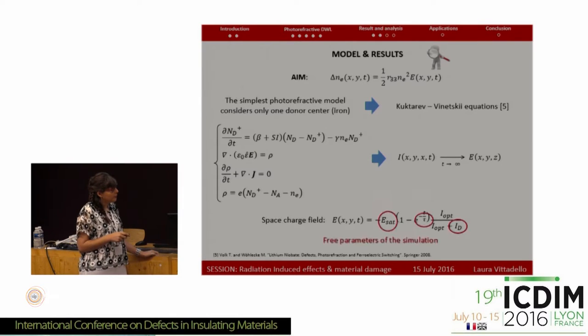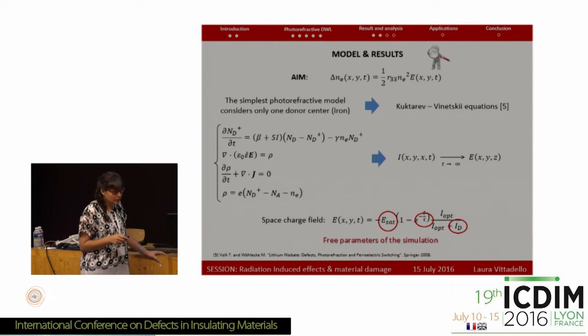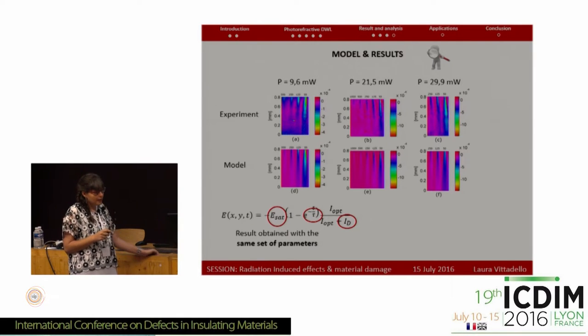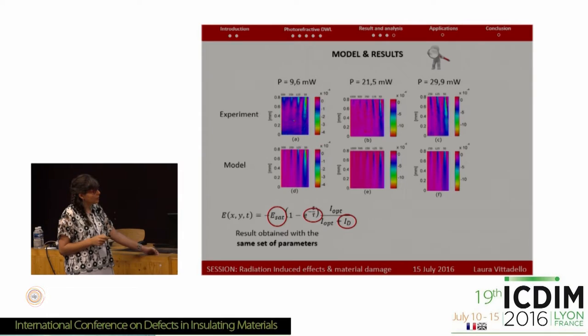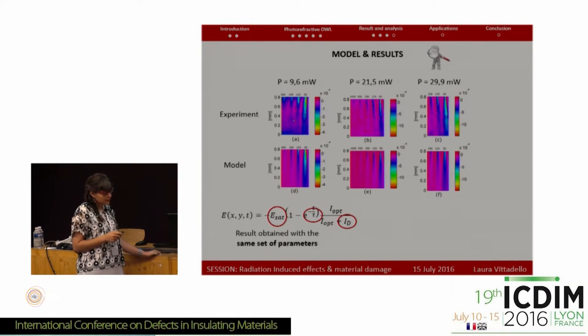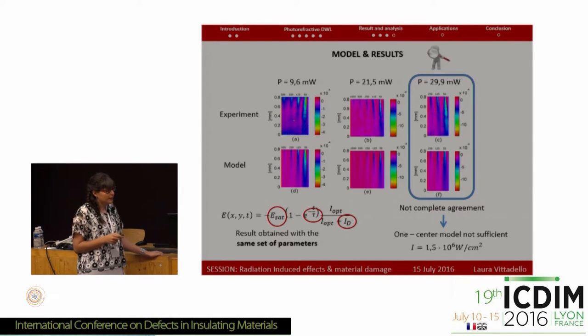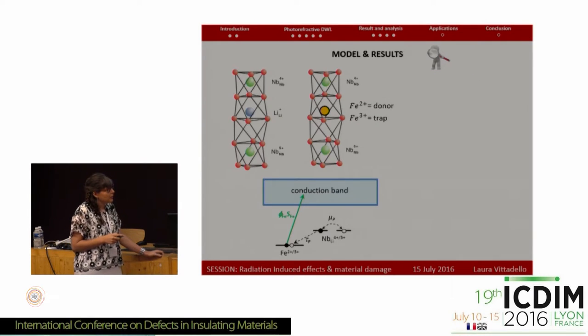In the formula there are some free parameters that we have to adjust in the simulation to better match our experimental results. I show the results here: in the first line is the experimental delta n map, and in the second line the modeled one. The agreement is very good between the two, obtained with the same set of three parameters. There is good agreement except for the last part of the experiment, where there is not complete agreement, because the one-center model is not sufficient to describe the situation completely — it works well only at low intensity.